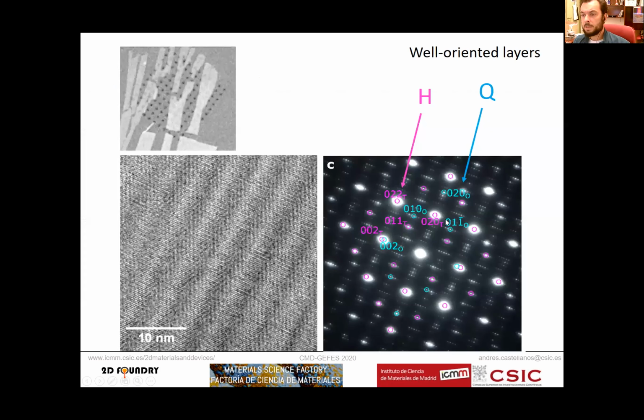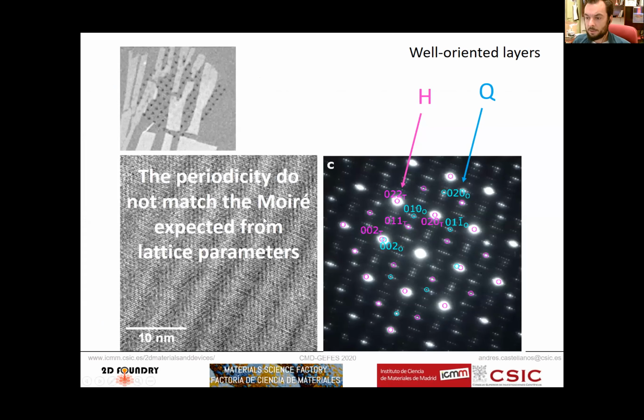And we can even see it if we do top view TEM instead of cross-sectional TEM. These are frankeite flakes on top of holes of a silicon nitride TEM grid. If we do this top view TEM, we can see that indeed there are fringes with a period that matches these waves that people saw in the 90s. And in the diffraction pattern, we can clearly resolve the two different lattices, the hexagonal one and the pseudo-tetragonal one.